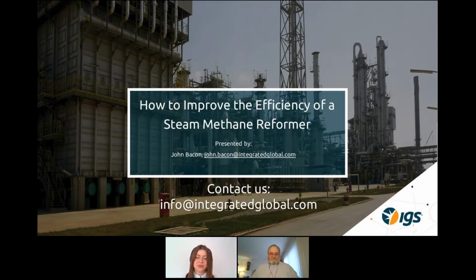By ceramic coating, we get uniform heat transfer. Could you please explain that? Yeah, if you think of an extreme situation where the refractory lining is a very, very low emissivity, the walls would act like mirrors and they'd reflect the radiation around inside the unit. So if you've got flames at the bottom, if you imagine a light bulb at the bottom, it would reflect from the sidewall mirrors onto the bottom tubes only. So that's where most of the radiation would strike the tubes from a very low emissivity lining.